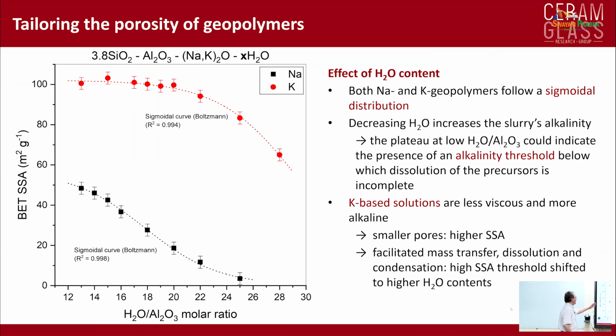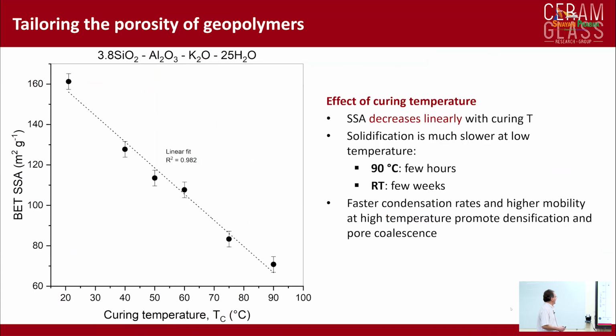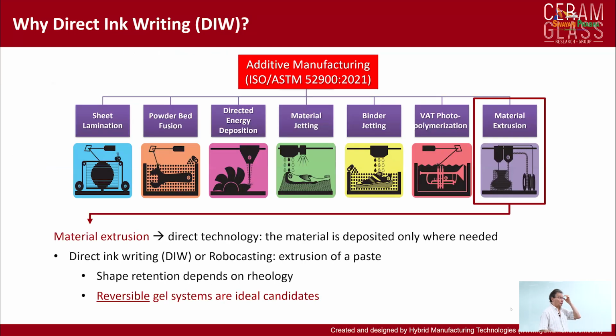Here you can see some of our experiments. We can reach up to actually 180 square meters per gram by controlling these fabrication parameters. And here you can see, for instance, by modifying the curing temperature, we can significantly decrease the specific surface area for the same formulation. So I will be talking first about material extrusion, and then I will be talking about binder jetting.